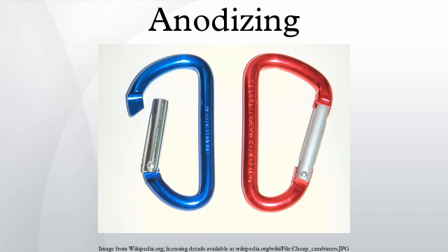For instance, sulfuric anodized articles are normally sealed either through hydrothermal sealing or precipitating sealing, to reduce porosity and interstitial pathways that allow for corrosive ion exchange between the surface and the substrate. Precipitating seals enhance chemical stability but are less effective in eliminating ion exchange pathways. Most recently, new techniques to partially convert the amorphous oxide coating into more stable microcrystalline compounds have been developed that have shown significant improvement based on shorter bond lengths.